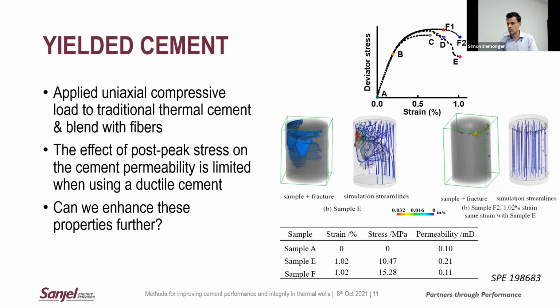And then, by comparison, when you look at a more ductile cement, a cement that's got these fiber additives, and it's taken to the same strain point, that's point F2 here, in the micro CT analysis there's no real indication of cracks or defects being observed. And this is down to a resolution of around 10 to 15 microns. So we had pretty good ability to see cracks that were going to be contributing to permeability changes. But when you then look at the fluid flow, you can see that you don't really see any significant change in your permeability relative to the original sample with no strain.